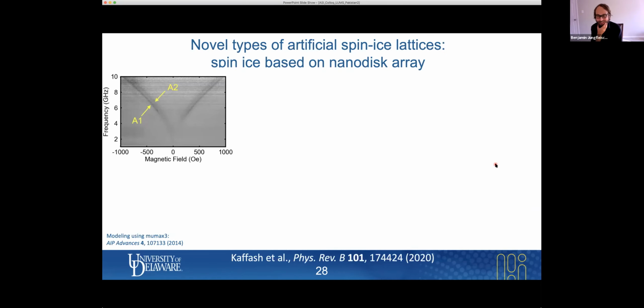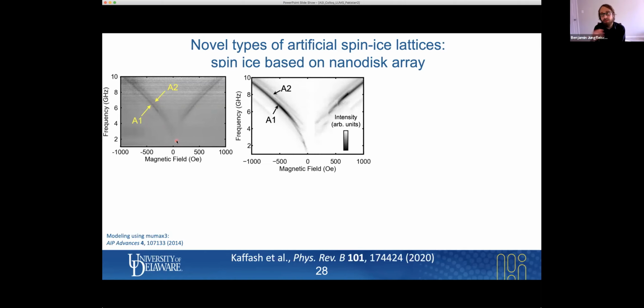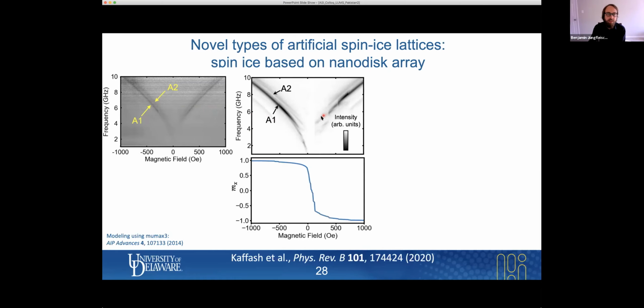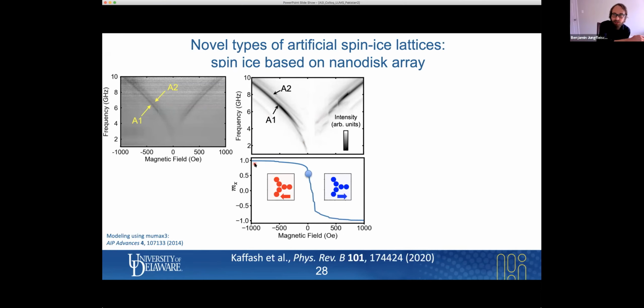So we performed our measurements like before, and we only see 2 distinct modes here, A1 and A2. We didn't see any vortex motion, unfortunately, in the experiment. But we also performed micromagnetic modeling. And you see here, again, pretty good agreement between experiment on the left and modeling on the right. And we can also perform static magnetization mapping using the modeling, using MuMax. So here you see we sweep the field from the saturated state in negative field direction to the saturated state in a positive direction. And I'm also showing here the color-coded image of the Mx component, spatially resolved.